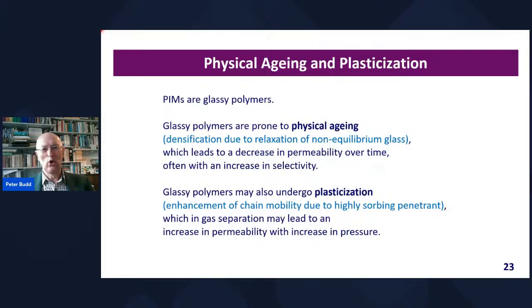field, some of the questions that people still have, some of the things that we're still trying to understand and improve on. And one of the things is a fundamental problem with glassy polymers. When we think about gas separations, the field is dominated by glassy polymers, but a glass is non-equilibrium. A glass is a polymer which is trapped kinetically in a certain state. And it can't move easily, but over a long period of time, there's just enough wiggle room that thermodynamics will do what thermodynamics does, which is, we're trying to build space into a polymer, and thermodynamics will always try to squeeze that space out if it possibly can. So that space is internal surface, it costs energy. Thermodynamics wants to get rid of that.